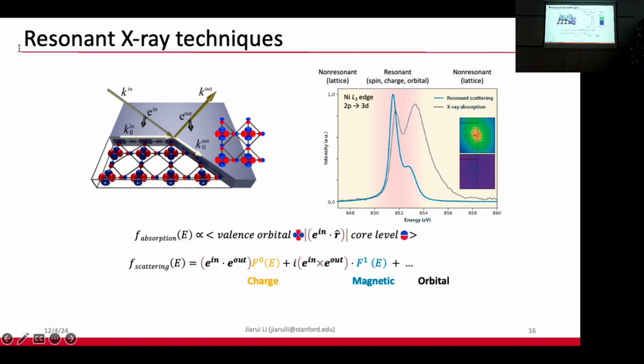So beyond simply the enhancement effect, the ability to control the X-ray photons also provides another probe to probe the anisotropy of these 3D electron orbitals. For example, in the absorption regime, by selecting the X-ray polarizations with respect to the orbitals, you can control the atomic transitions, or forbid certain atomic transitions. And in the scattering channel as well, by selecting the incident and outgoing X-ray polarizations, you can selectively probe the charge, magnetic, or orbital degrees of freedom.